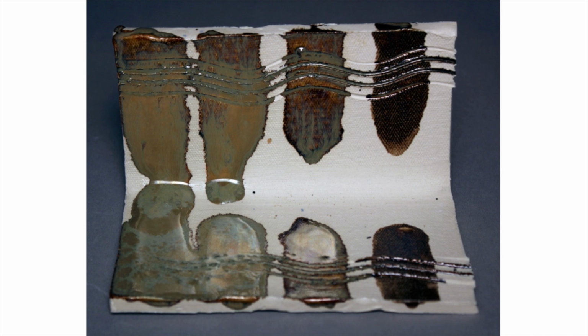I use this glaze all the time. This test tile shows how runny it can be depending on how it is mixed up. More water was added before each consecutive brush stroke, going from very thick to very thin. Note how runny it is when mixed thickly, as shown in the first stripe on the left, whereas it can be nice, as shown on the right, with just the right amount of water in the third stripe. Glaze recipes never list how much water should be added. Experience is the best teacher.